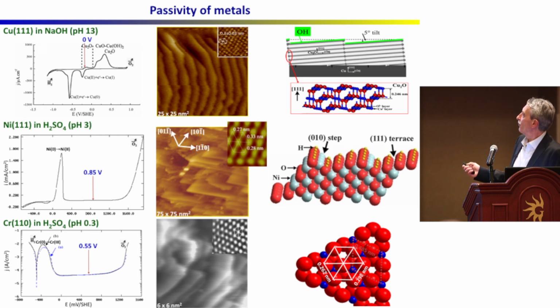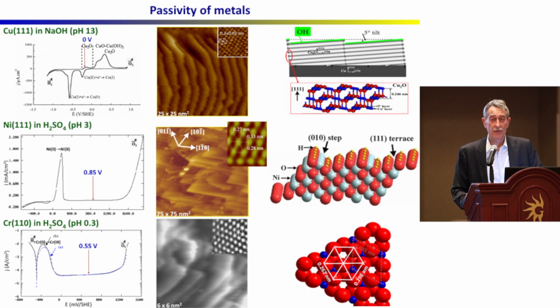So we know that the film is crystalline, but we have these fairly narrow terraces and steps, and this is the model. You see the tilt between the dense planes of Cu2O and the substrates. And we can determine this tilt by looking at the width and height of these steps. And this is just a few degrees, 5 degrees in that case.